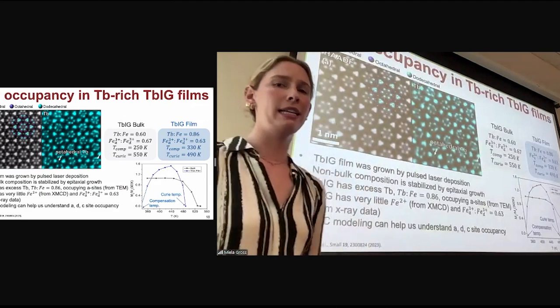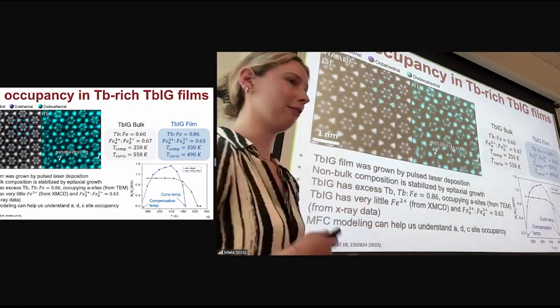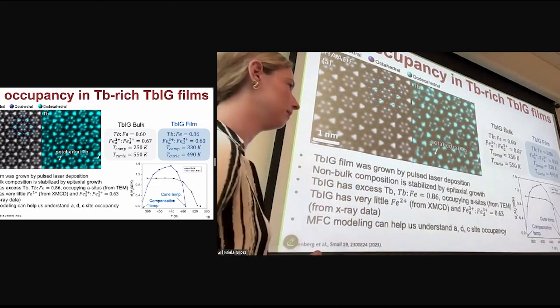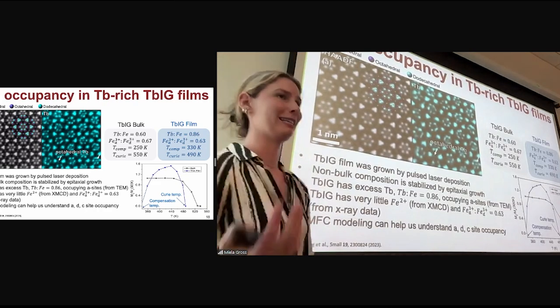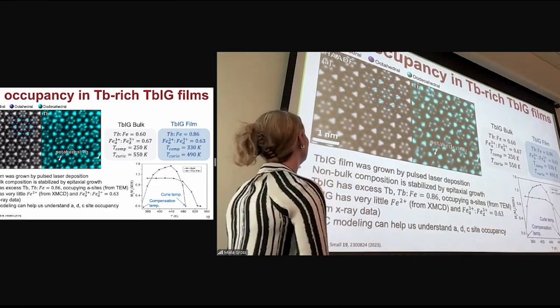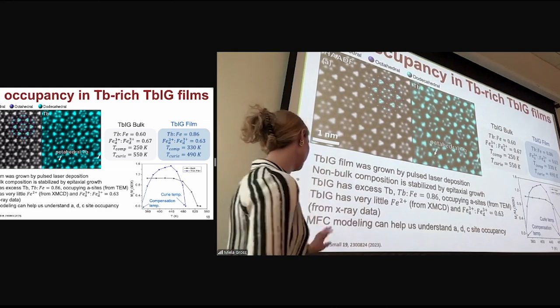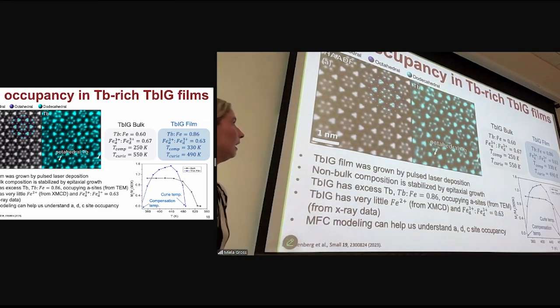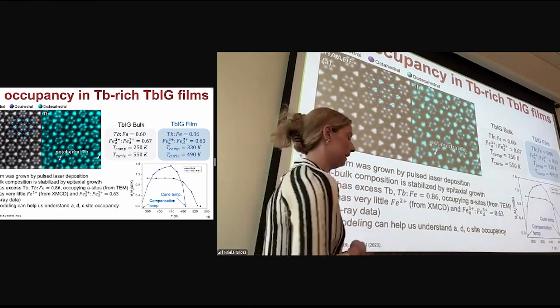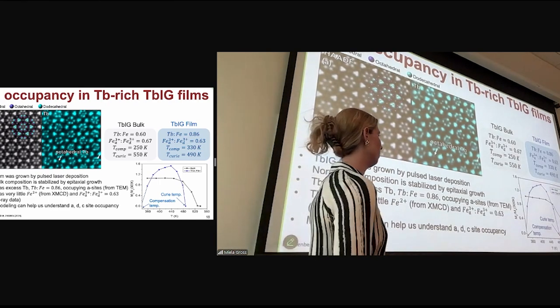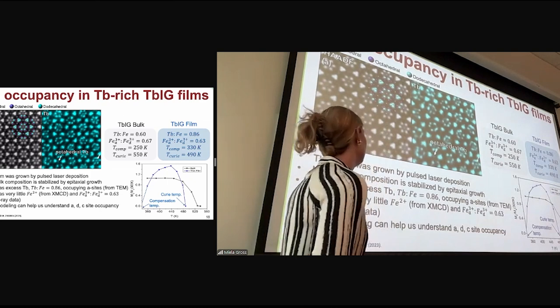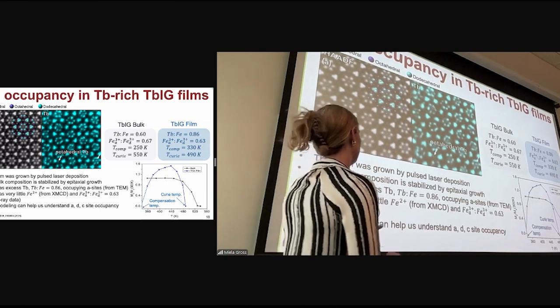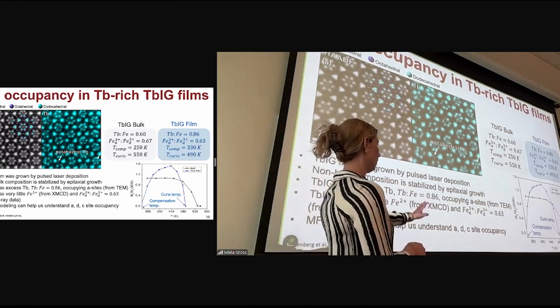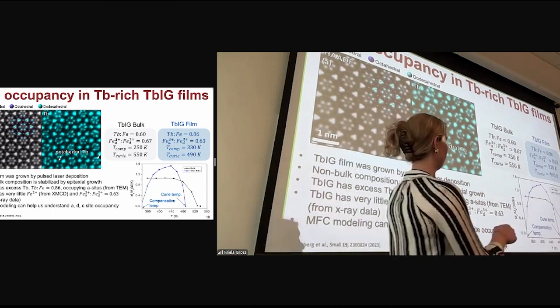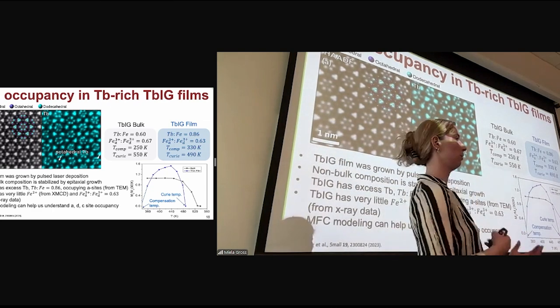So now I said that I could expand this model to the non-bulk stoichiometries of epitaxial films. So this is an example of how we do that. Terbium iron garnet was grown by a colleague, Ethan Rosenberg, and grown to be extremely terbium rich. He was able to stabilize this non-bulk composition by epitaxial growth. And he found from TEM elemental mapping that the terbium to iron ratio was 0.86. And what we'd expect in bulk is only 0.6, so it's super terbium rich.